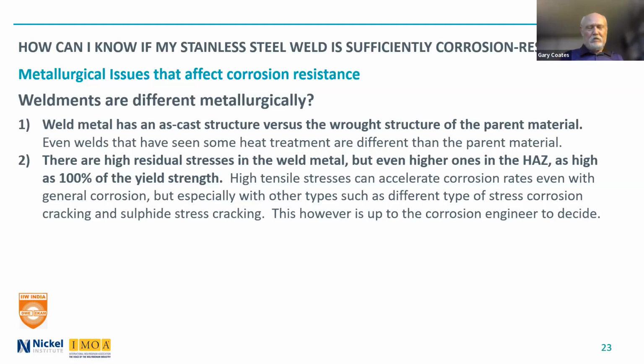Yes, if you have an environment with high chlorides and the temperature is up to, we normally say it's most common above 40 degrees C, but it can actually happen as low as room temperature, ambient temperature, 22 degrees C. This is really something for the corrosion engineer to decide. And if he chooses 316L and he thinks that will resist the stress corrosion cracking, well, that's his call. But we know that 316L, when it has very high residual stresses, is very susceptible to chloride stress corrosion cracking. And you might question him about that. He may not know that. And it's really a whole separate discussion there, but certainly it's not up to the welding engineer to decide.